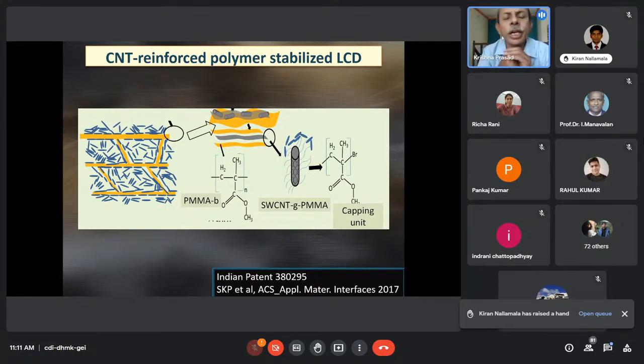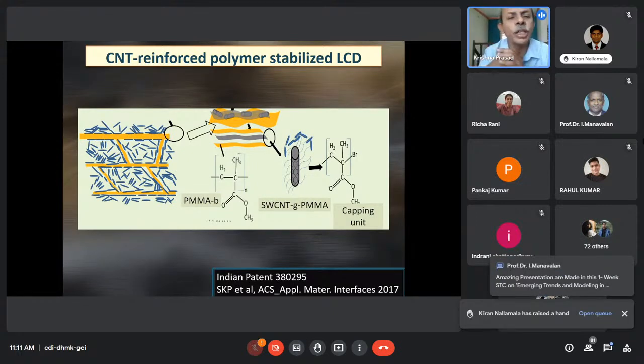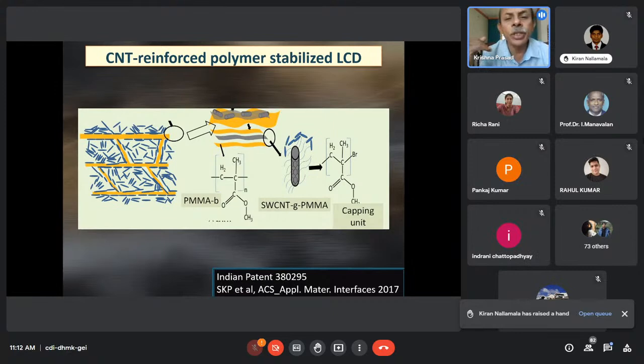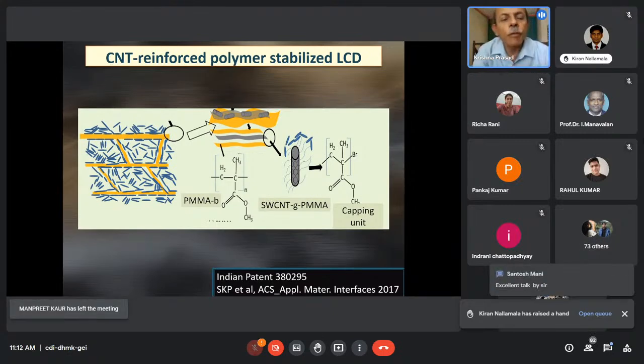But the problem in putting into these kinds of architecture, on one hand, we want the CNT to be present in the system, but on the other hand, we do not want CNTs to be interacting much or in a direct fashion with liquid crystals. What is the reason? Main important reason is the CNTs have a large conductivity. And once you put a large conductivity into electrically switching devices, you are spoiling the entire show. Because once you make the system conducting, you're going to short the two substrates. And so therefore, no electric field can be applied. Or even if you apply, there's going to be a large double electrode kind of creation happening. And so therefore, the internal fields are going to be very small. And so therefore, you cannot allow the CNTs to be getting into the liquid crystal region, but select and go only to the polymer regions.